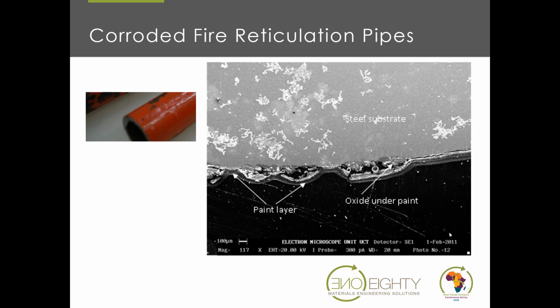So we needed to see what the paint coating looked like in areas where it was still intact and follow the failure to where the paint started to peel off. To do that, we mount the sample in a special type of resin, which has very good edge retention. We call it edge retention. That means that it holds the paint coating and any contamination between the paint coating and the steel very tightly on a microscopic level. We then prepare the sample by grinding and polishing it, and then we take it to what we call an electron microscope. An electron microscope is an amazing high-level technology item to solve this real-world problem, and it uses electrons to create an image. So it scans the surface and creates an image.